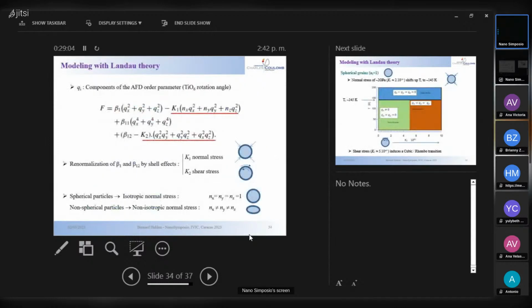To know a bit more about that, we developed the Landau theory, and we renormalized these B1, B11, and B12 parameters, which are the usual parameters for the Landau theory, by terms which are underlined in red here. K1 corresponds to a normal stress, K2 corresponds to a shear stress, and the indices nx, ny, and nz correspond to a spherical particle if n equals 1, and a non-spherical particle if nx, ny, nz are different.